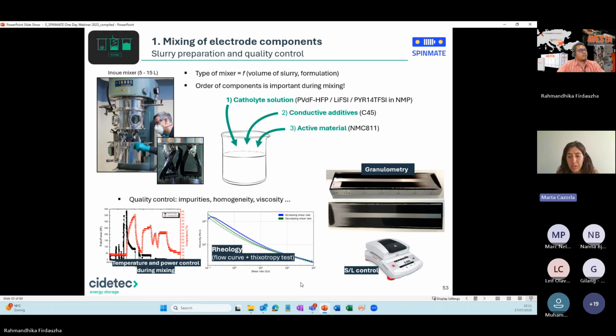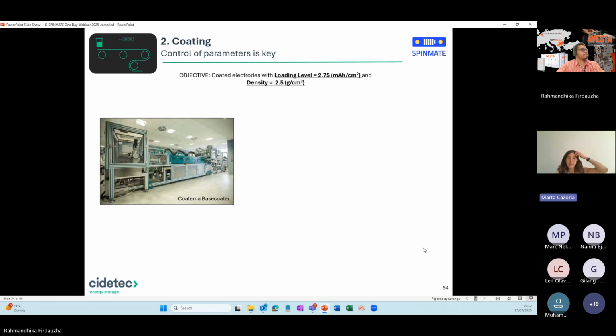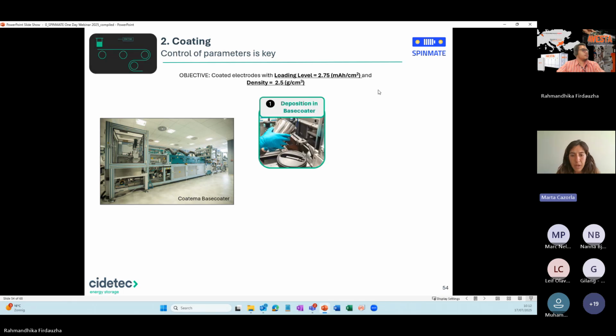And during all this process, we monitor very well the solid-liquid ratio, because we need a certain amount of this ratio to allow the coating process to be smooth. So in the next step comes the coating. Here it's very important to define properly which loading level, so how much active material we want on our layers, and also its density. This will be controlled afterwards with the calendaring, but already we need to have it clear.